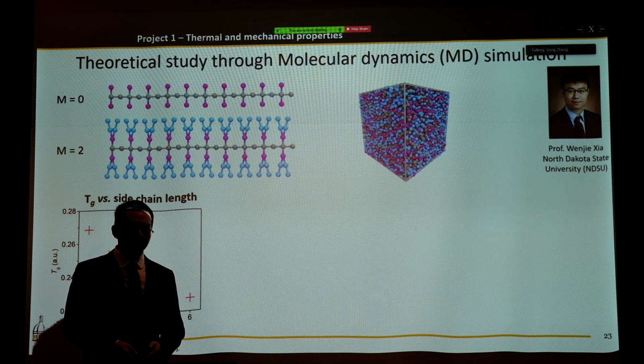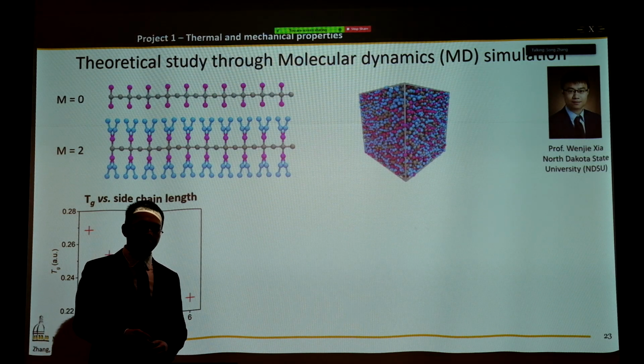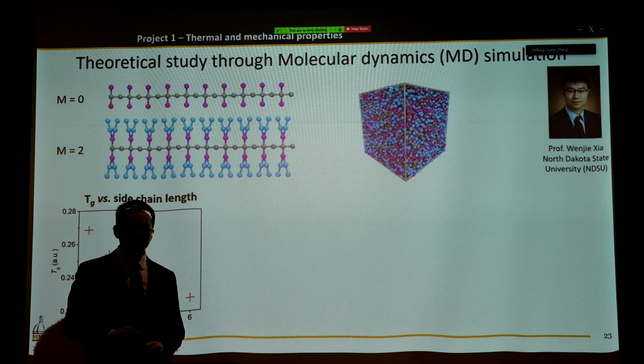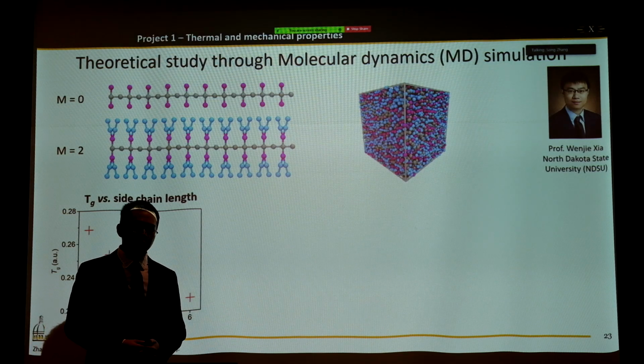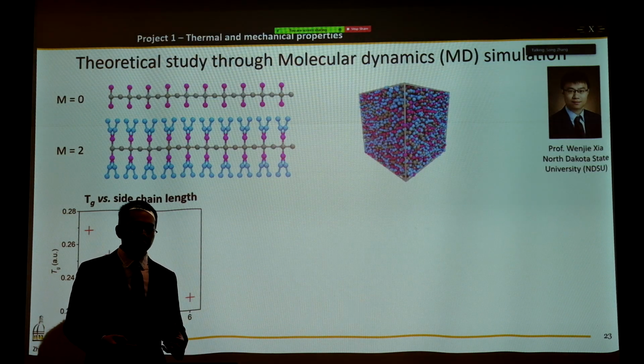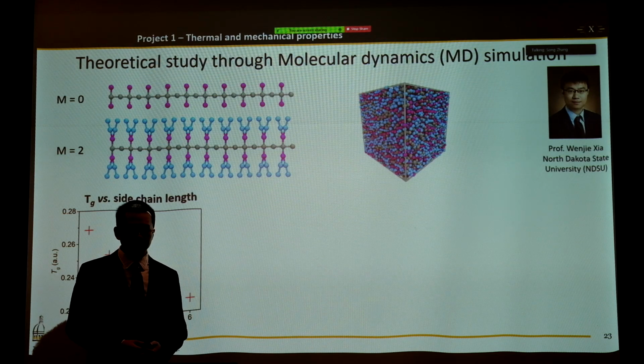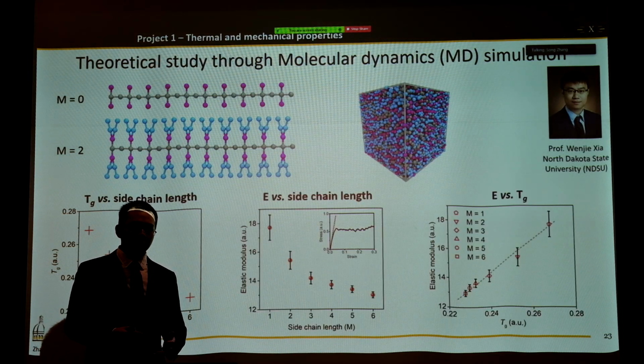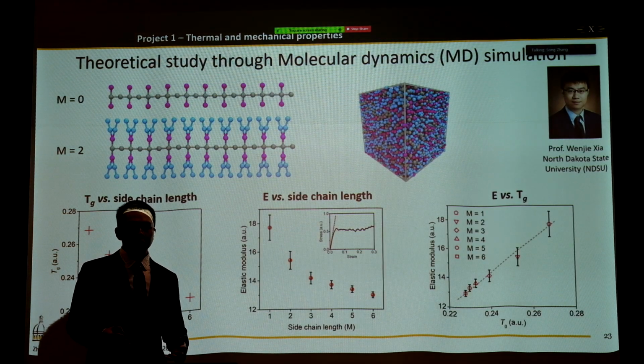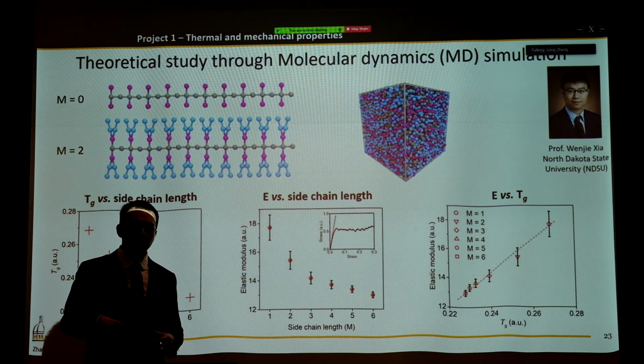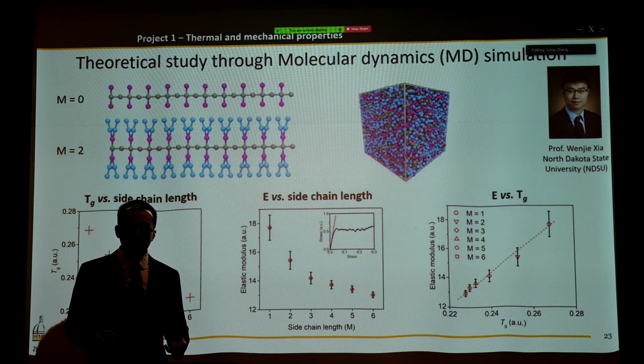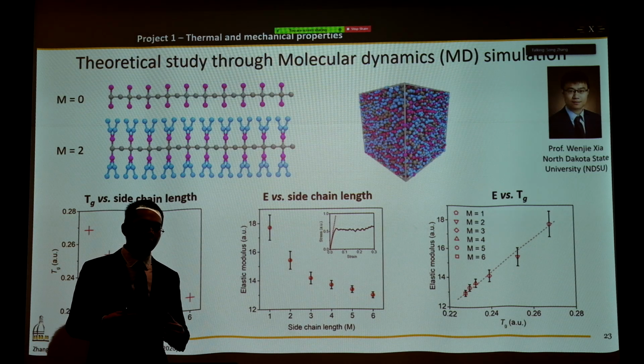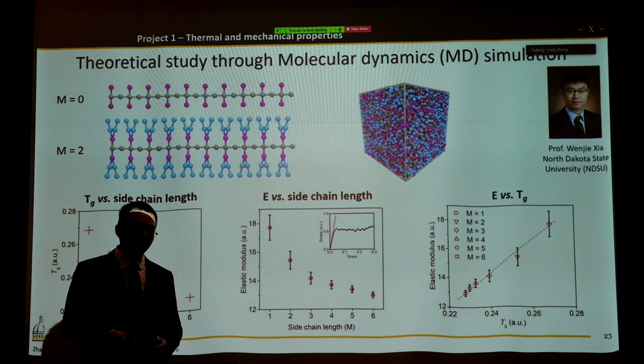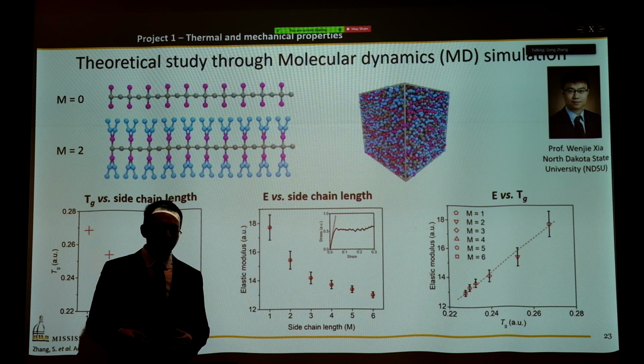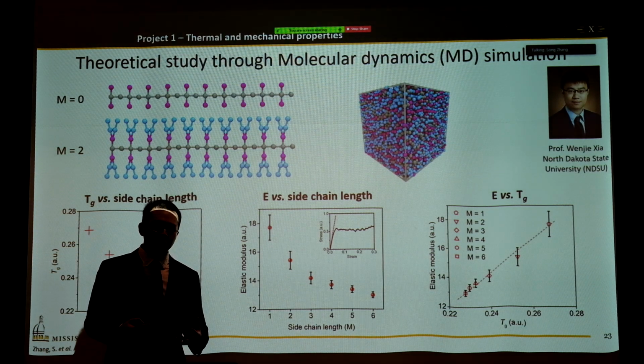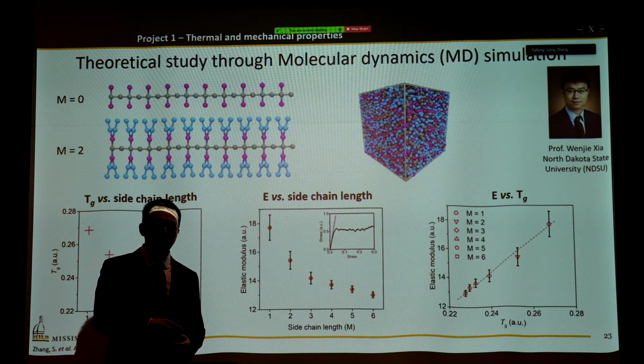So we start with a very sharp decrease in Tg, followed by a very slow decrease. That can be understood because with more side chain, your polymer is behaving like the side chain itself. And if we simulate the elastic modulus, we also see a linear relationship between elastic modulus and Tg, since the molecular dynamics simulation does not provide crystalline domains. Okay, now we have this qualitative understanding of how side chains affect Tg.